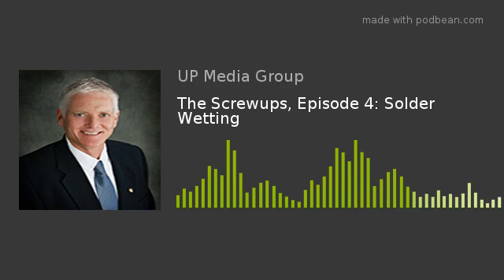So that's one of the things that we run into fairly regularly, and I would encourage listeners, if it's one component that's not soldering, to investigate the component and not the paste if the rest of the board is meeting your quality requirements. We have to really focus on where the problem is. We're more than happy to provide counsel. It's just that it's probably not the paste. Sometimes, but not usually. So that's the anecdote from the field. That's very, very common, actually.